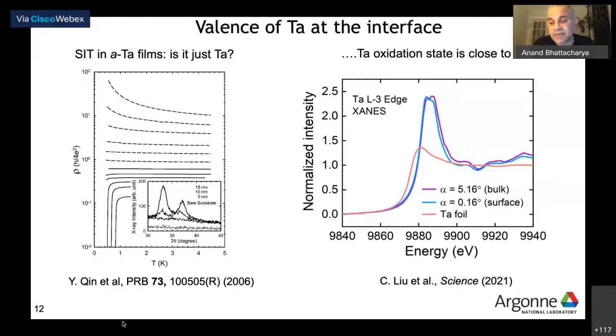For example, tantalum could leach out with the surface. The oxygen could be blown away, and you could be left with a thin layer of tantalum. Maybe it reduces very easily, and then you get a layer of tantalum, and that could superconduct. In fact, ultra thin films of tantalum have been known to superconduct with a TC comparable to what we see in our samples, right?